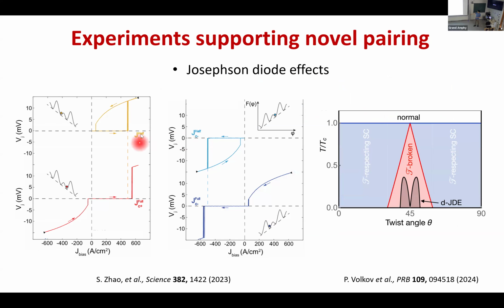Another thing is they observe some Josephson diode effect. This is not really the standard definition of the Josephson diode, but it depends on how you prepare the state. If you prepare the state such that you go from high current back, and then you sweep the current, you have a critical current which is smaller than the current when you go to the negative direction and then do the sweep. After this paper, theoretically they claim that this is consistent with the expected behavior for d+id, because d+id breaks time reversal symmetry, and then you are not exactly at 45 degrees. This is around 40 degrees. So then you also break the inversion symmetry. So you satisfy these two conditions, you have some diode effect. So the current is not symmetric.